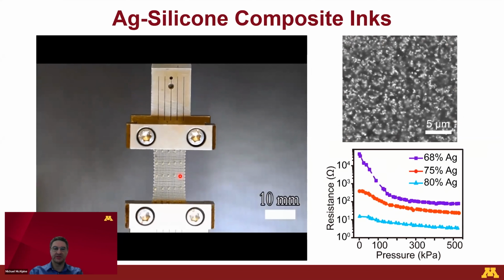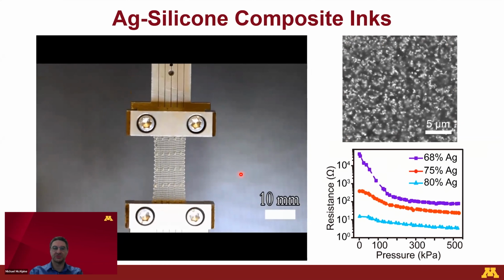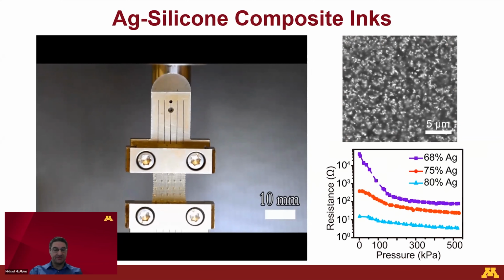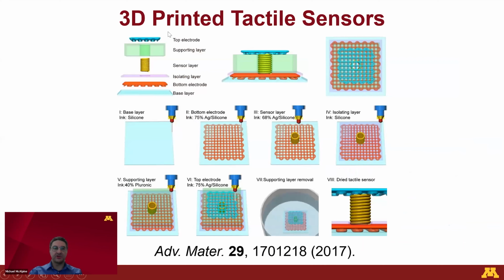And from there, this is what it looks like with the particles mixed into that ink. So it's almost like a fabric that you're printing here that's electrically conductive, that's entirely 3D printed, but also stretchable as well. And that means it can function as sensors depending on how much of the silver you load into the ink. If you load too much silver, then it's highly conductive. If you load not enough silver, it's not very conductive at all because the silver particles don't touch one another. And if you can meet the threshold called the percolation limit, that's sort of halfway between those two zones, then you have a highly sensitive region where the particles are initially separated, and then as you compress them together, they form a conducting pathway. And therefore you have a high change in resistance that can be used as a sensitive sensing platform using this 3D printed composite ink.